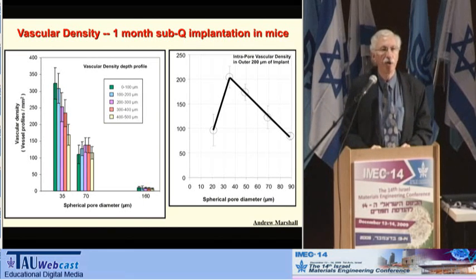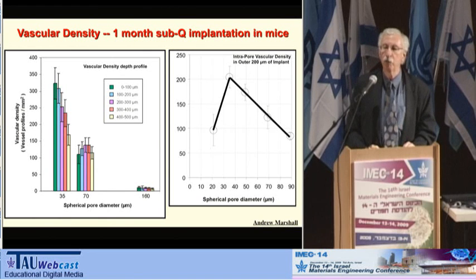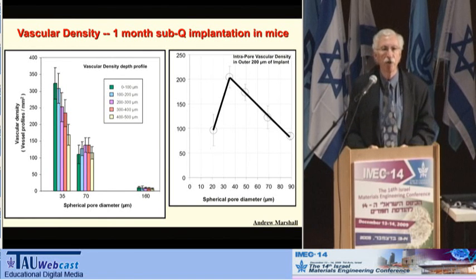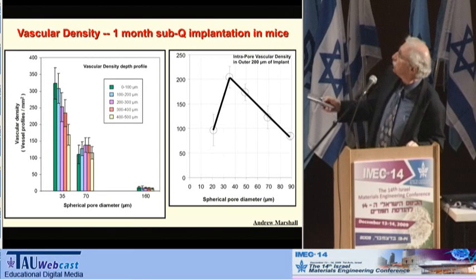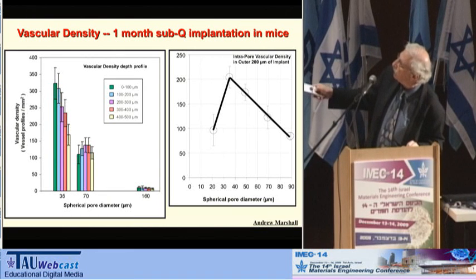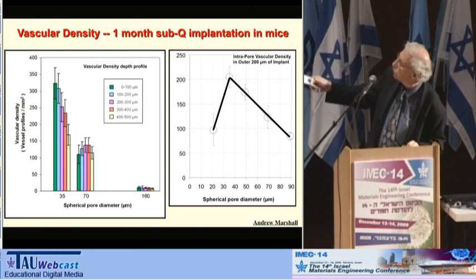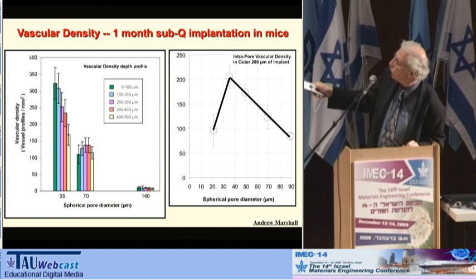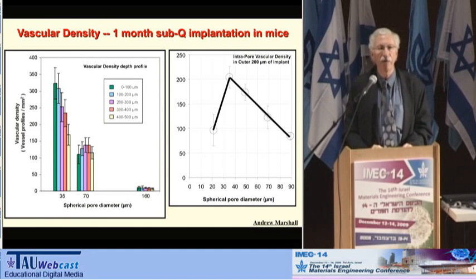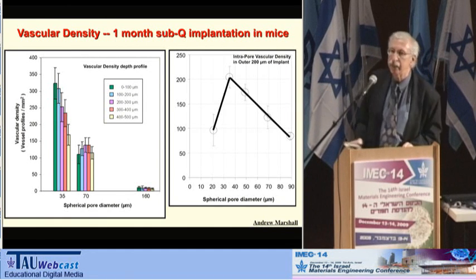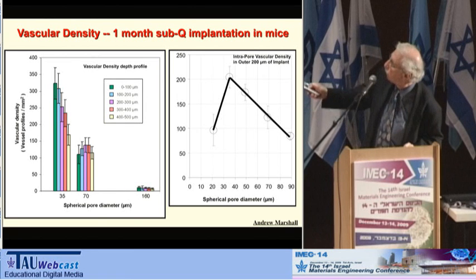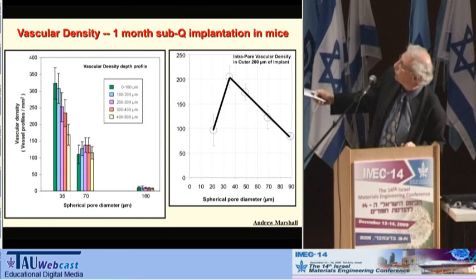And blood vessels are a sign of a regenerative, reconstructive healing versus that collagenous scar. So if the pore size was just right, we got a very profound level of blood vessels produced in here. If the pore size was up around 160 microns, there was hardly any blood vessels. And most tissue engineering scaffolds are up around this size.